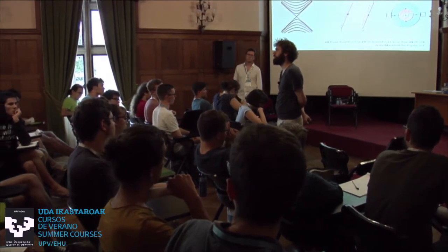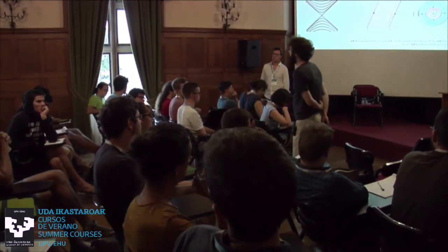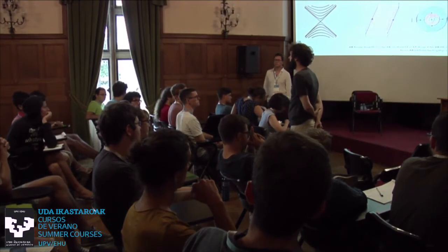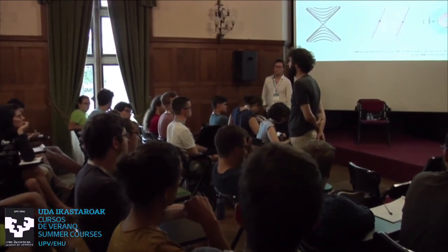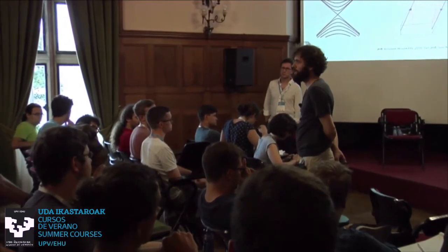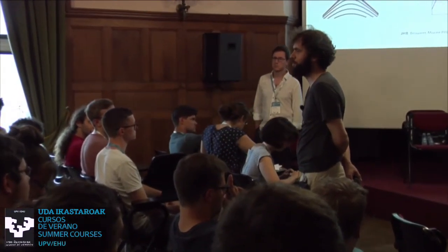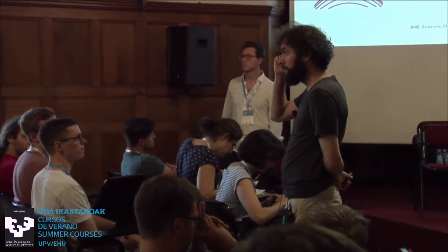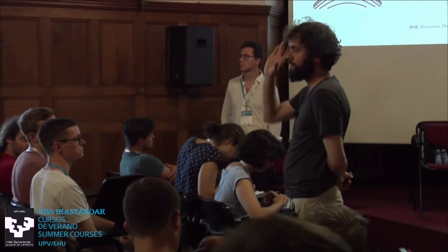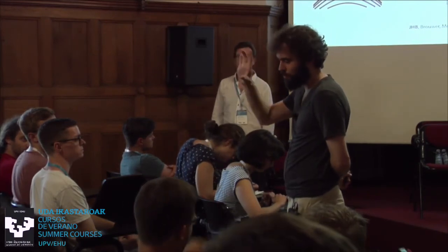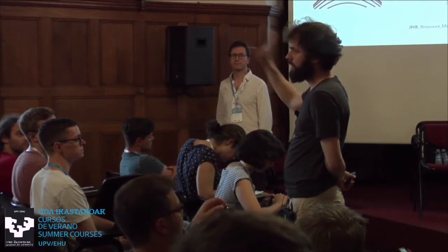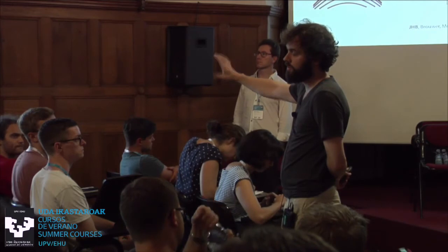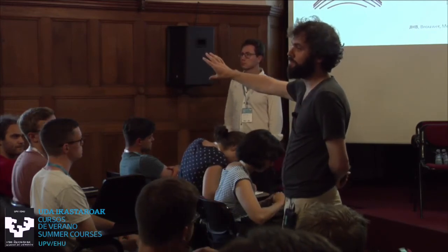No, that's right. So this is a matter of length scale. Strictly speaking, if I keep the circumference of the wire fixed, and then I take L to infinity, then yes, it will basically always be zero except for a very fine-tuned point. But if I look at experimentally relevant values, for example, a few hundred nanometer circumference and a micron long wire, let's say, then you're very far from the localizing regime.